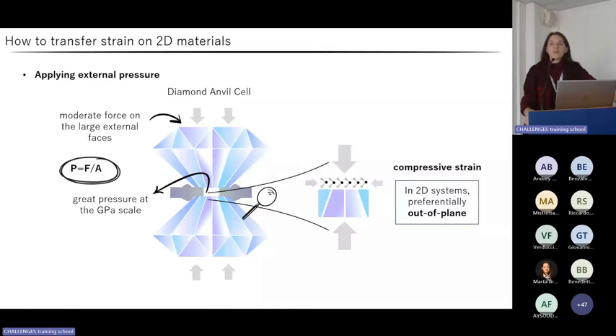A well-established method to transfer a compressive strain is high pressure, which is not limited to the case of two-dimensional materials. To apply high pressure, we use a device called a diamond anvil cell, or DAC, formed by two opposing diamonds with large external faces of the order of millimeters and small internal faces, called culets, of the order of hundreds of microns. In that configuration, by applying a moderate force on the large external faces, we can obtain a pressure at the gigapascal scale, that is 10 to the 4th atmospheres, in correspondence with the culets.